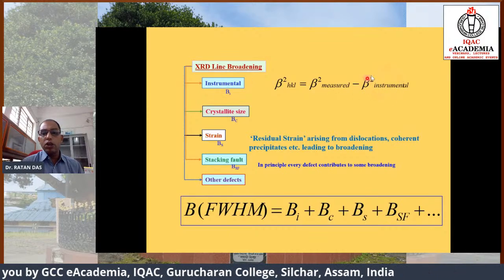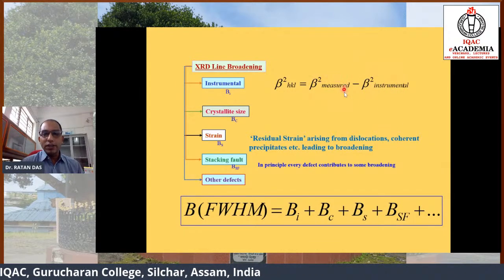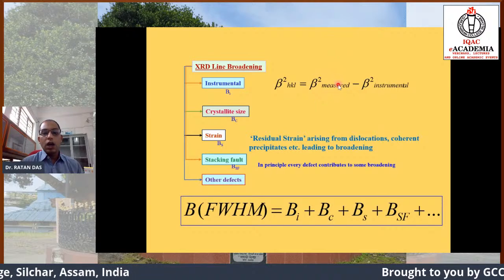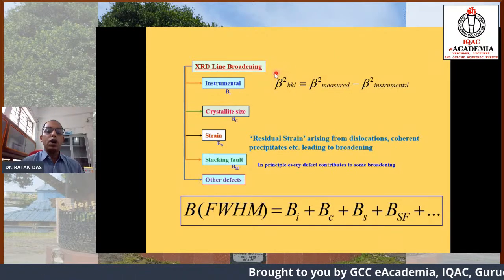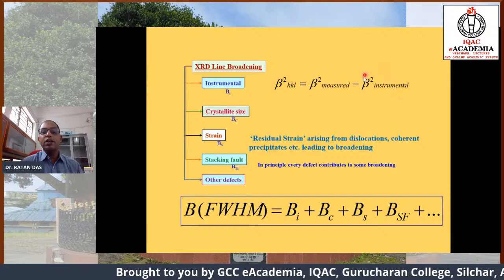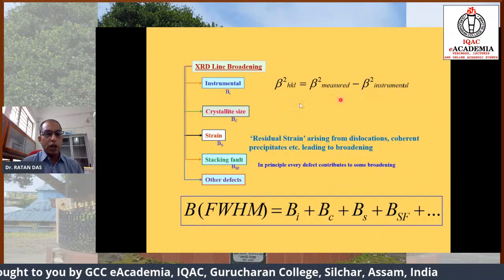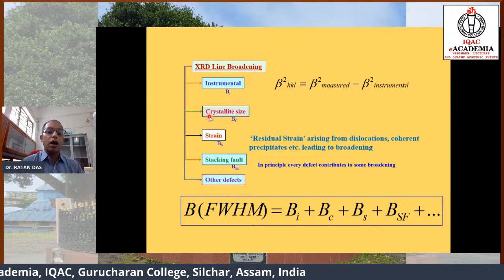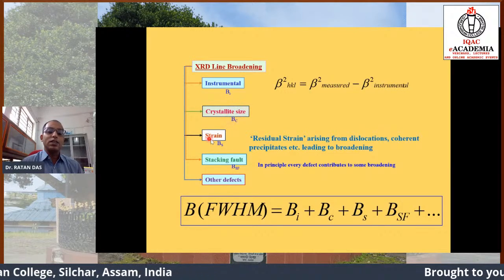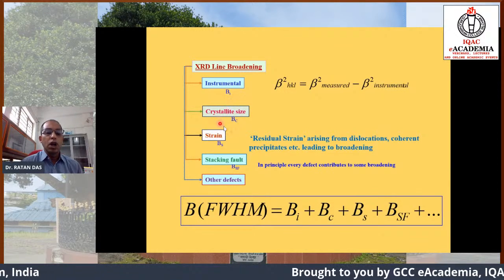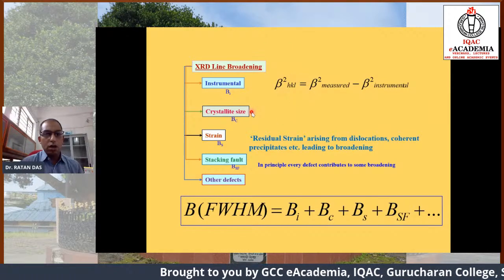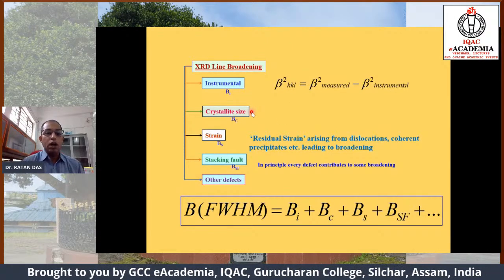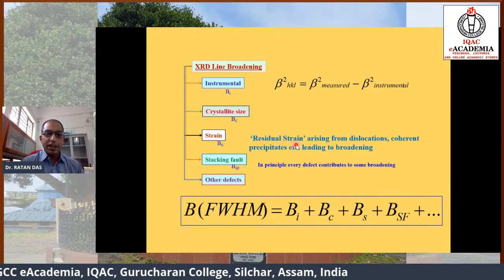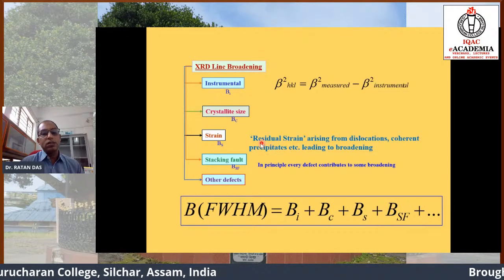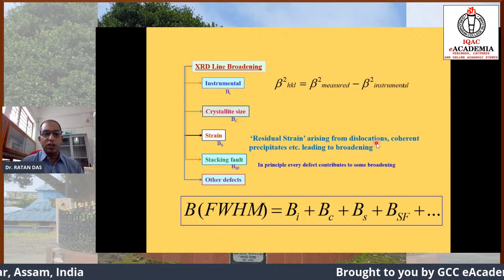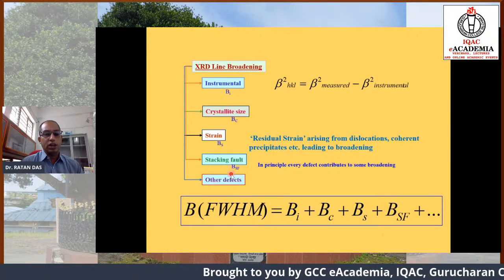That instrumental broadening we may get rid of from the measured broadening, and we can obtain a suitable broadening after getting rid of the instrumental broadening. And in the X-ray diffraction pattern, I have told you that crystalline size and strain also play a role in broadening the pattern. So what is called residual strain, or we may say intrinsic strain, arises because of dislocations, stacking faults or other defects.